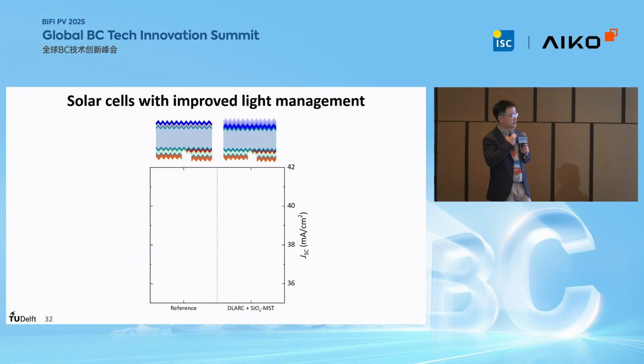So we implemented such an optical design into the device, and as a reference, there is a 23.59% efficiency solar cell on the left. That had a current of around average, slightly below 40 milliamp per square centimeter. But for the best-to-best device, after implementing such an optical design, we could boost the average JSC and the best JSC to over 41.5 milliamp per square centimeter.